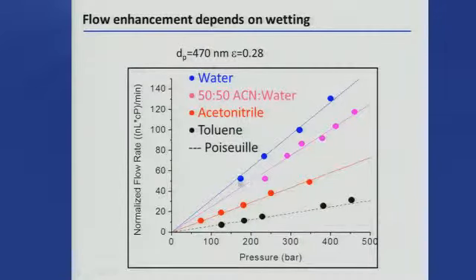And so toluene matches Poiseuille flow very well. The rest of these lines are linear fits in order for us to get the slope and determine the flow enhancement. And so this is really good evidence. This is very convincing evidence that we have slip flow, and that's the explanation for the better chromatographic performance. And so with this, we were able to get the paper published as a JACS communication, and then a theoretician got interested in this and improved the theory as well. And so now the results agree pretty nicely with theory, accounting for the slip flow as well as accounting for the fact that the protein doesn't reach all of the interstitial volume, and so it stays a little bit more in the center of the flow stream, and that explains the results that we're getting.